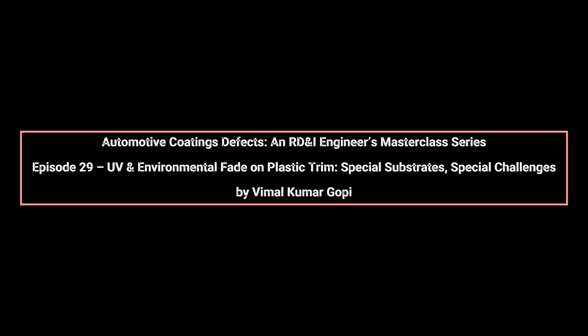UV radiation is the primary driver of fade. Plastics absorb UV differently from metals and often transmit energy directly to the coating layer, causing chain scission, oxidation, and additive depletion at a faster rate. Polymeric dyes and pigments in the coating absorb light energy, converting some to heat, which increases local substrate temperature and accelerates degradation. Unlike clear coat over base coat systems, plastic trims often rely on a single-layer topcoat or pigmented coating to deliver both color and protection, making them more vulnerable to photochemical attack.